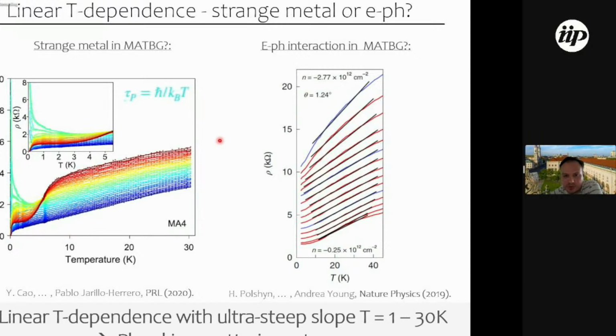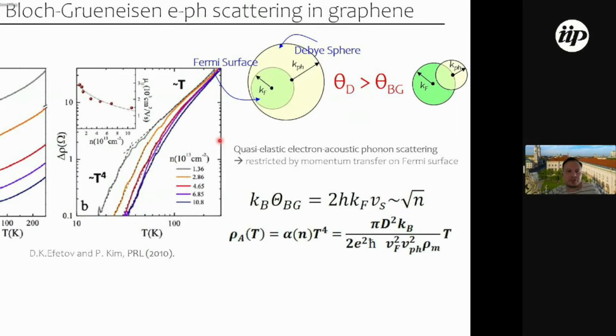So to do that, let me tell you what we know about electron-phonon scattering in graphene. This is work which I did in my PhD. This was my first PhD paper, actually back in 2010. And I back then investigated just the electron-phonon interaction in single-layer graphene. So no twist, no second graphene layer, no interactions. This is really just boring single-layer graphene, where the transport properties are completely explained by electron-phonon interactions.